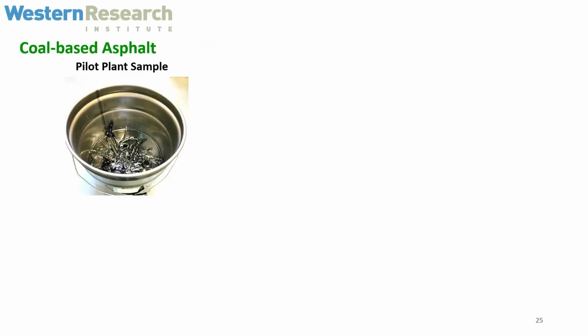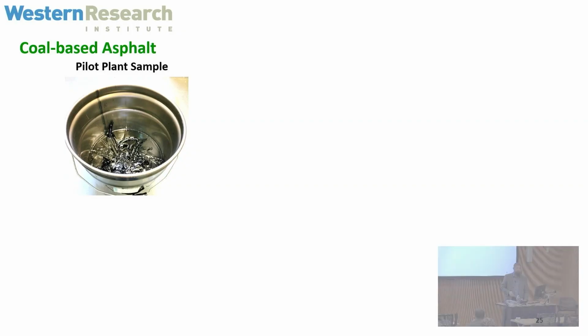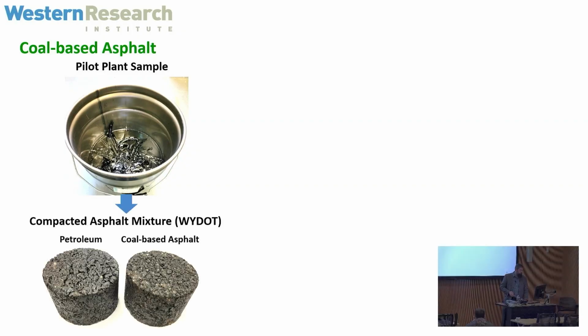So we've been able to produce larger quantities of some of these materials. This was produced at a pilot plant. This material was then given to the Wyoming Department of Transportation, where they made what's called a mixture. You put it with all the rocks and everything else, because that's what really gives the material the stiffness and the strength, is all the rock and everything. Because the asphalt binder in your pavement is only 5%. So they made this, they compacted it, they said it seems like it works great. One benefit is it didn't have any smell. They were super surprised because asphalt always has this kind of sulfur smell.